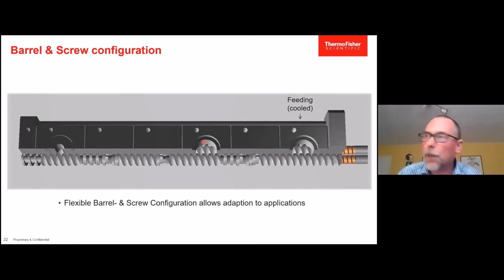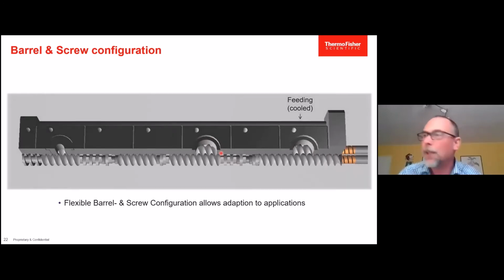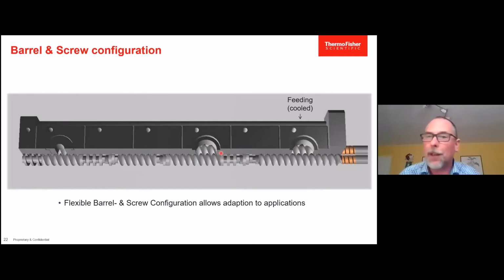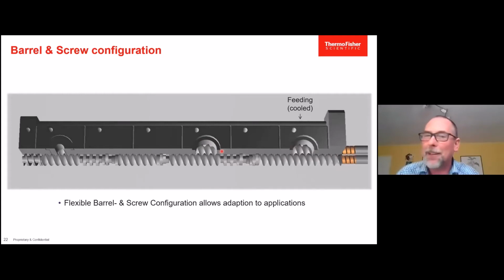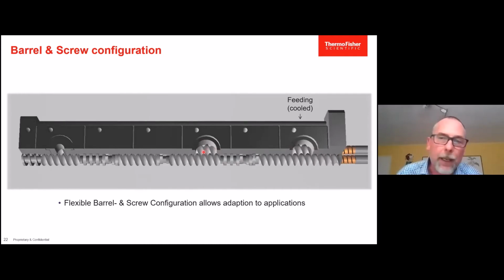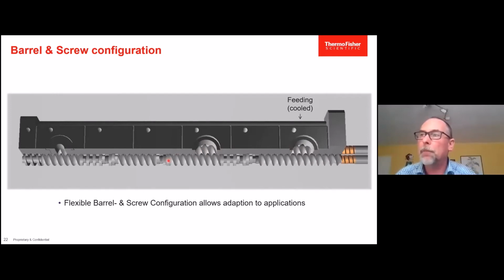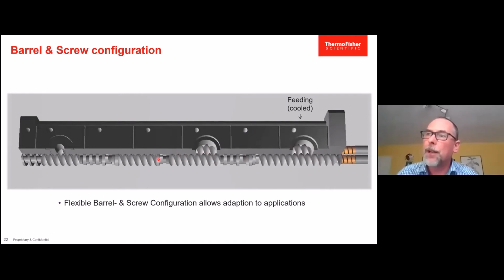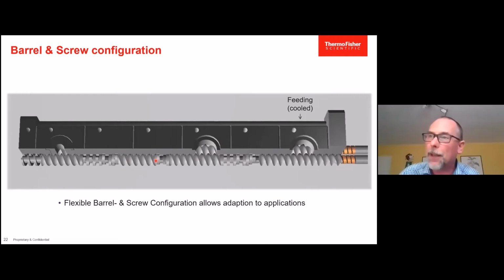Here is another opening. Typically, we would add here a second component to make a compound, be it a colorant, an inorganic filler, but it could be something like a wood composite, or in terms of pharmaceuticals, it might be some API, some plasticizers. So never mind, it's a big opening for, let's say, powders or granules. It could be closed and could be with a small tube to inject liquids, for example. Also, this secondary component needs to be mixed inside, so there are various mixing zones. Another transport zone, mixing again, an open transport zone, for example, for degassing.